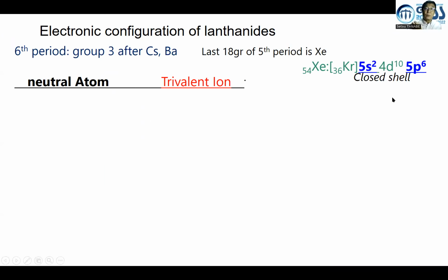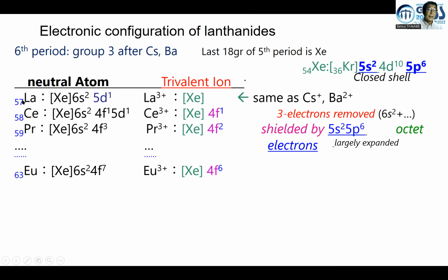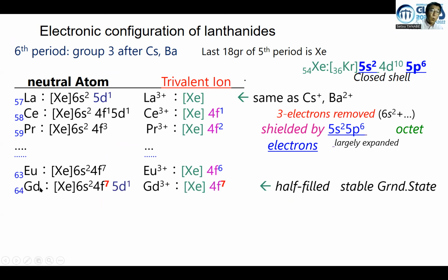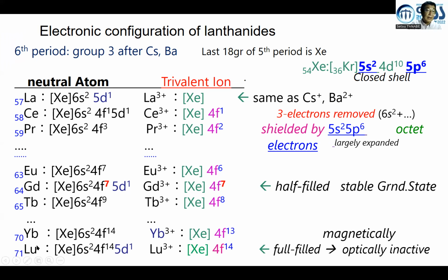So we can consider the electronic configuration of the 15 lanthanide elements, starting from lanthanum 57, cerium 58, and praseodymium 59. And in the middle is gadolinium 64, having 7 4f electrons. Instead of having 8 4f electrons, it prefers a half-filled state and puts 1 electron into the 5d orbitals. This is a very unique feature, which is also observed in chromium among the 3d transition metal elements. And similarly, the last, lutetium, because the 15th electron cannot be accommodated into the 4f orbital, it must be occupied in